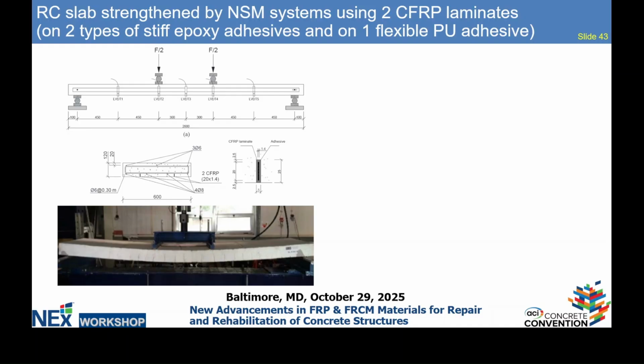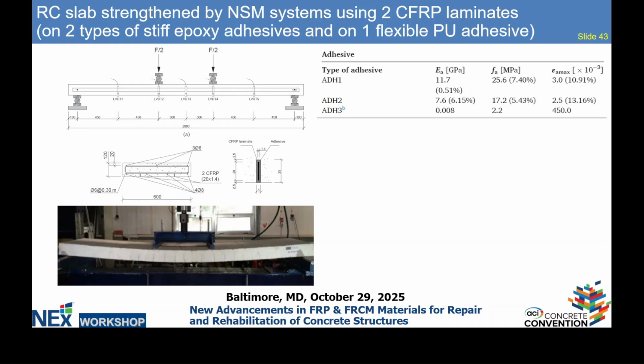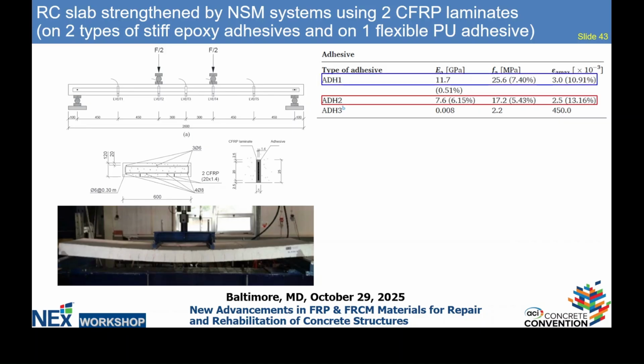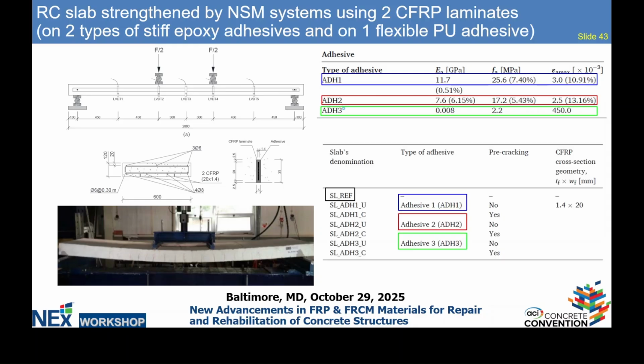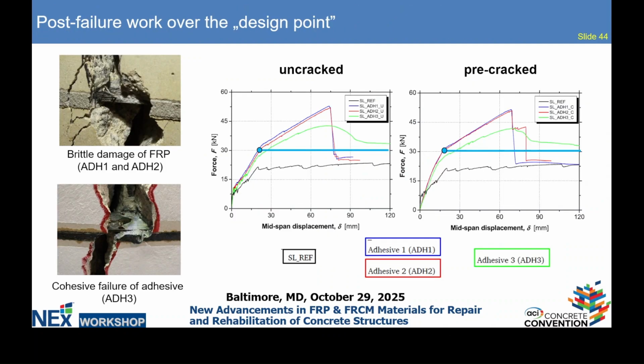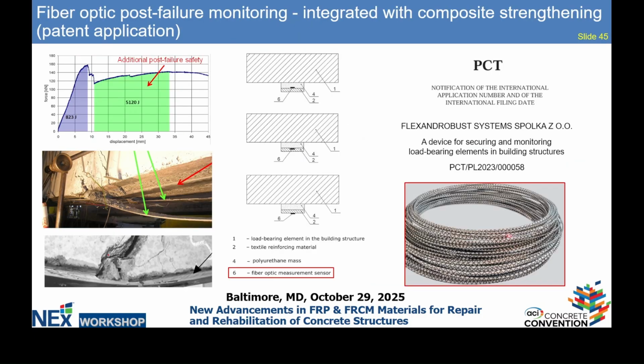So confirmation from the NSM system, research done in Portugal at Minho University, 2 carbon fibers with epoxies and 1 carbon fiber with polyurethane. We tested it in pre-cracking and after-cracking repair. You can observe that the blue one and red one are epoxy, green one is polyurethane. So you can clearly see that there is sudden failure, but with polyurethane, we have stable behavior, almost working after the damage, post-failure behavior. So this is safety.